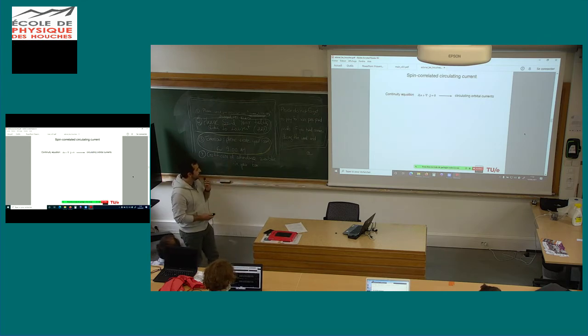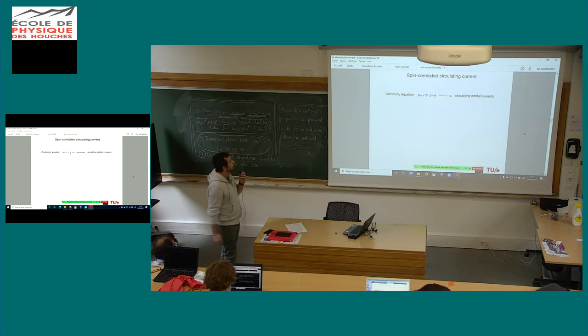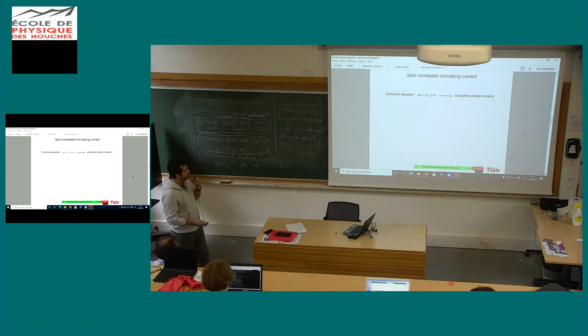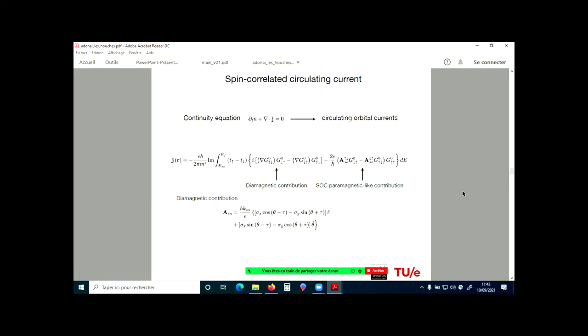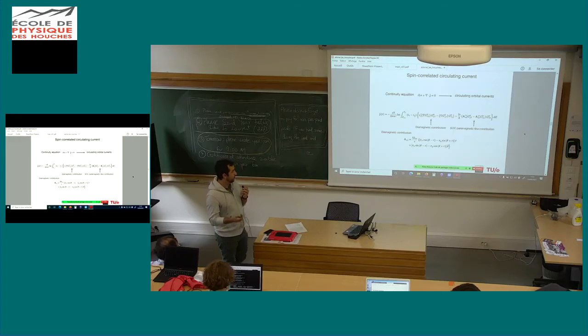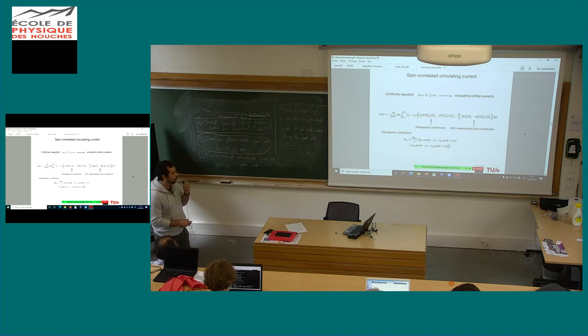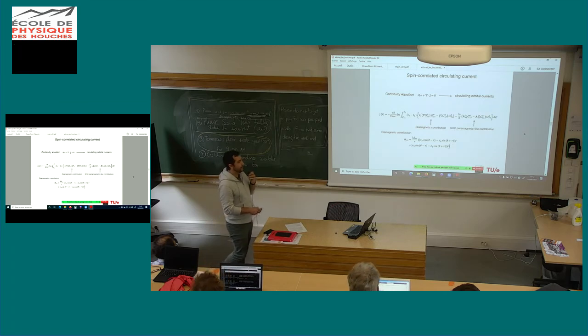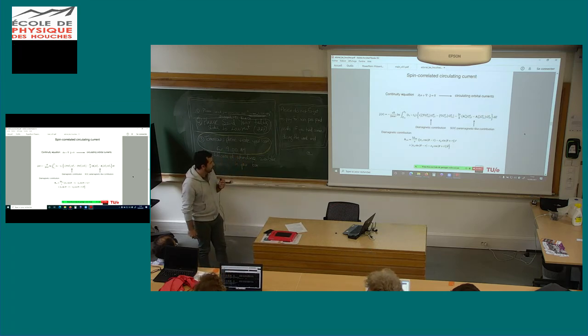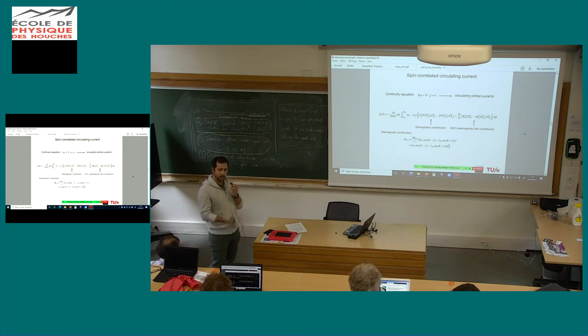So using that, the next step was to find a suitable current operator for the problem. As mentioned last week, there was a remark in Felipe's talk about the correction to the current due to external fields. And here something similar is going to appear, but we don't have an external magnetic or electric field, we have an effective spin-orbit field. And this will give rise to a second term that's called the paramagnetic contribution to the current. So this expression satisfies the continuity equation, which is important because this is a ground state property, so it's a steady state. We have no charge accumulation, so this is nice.